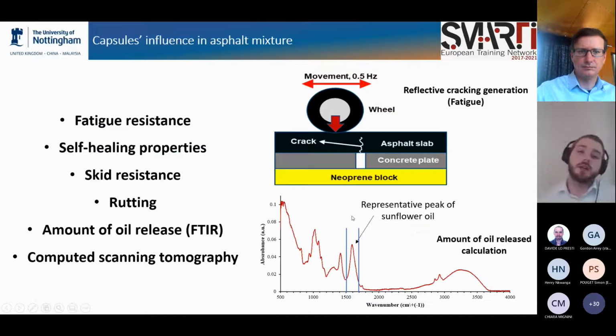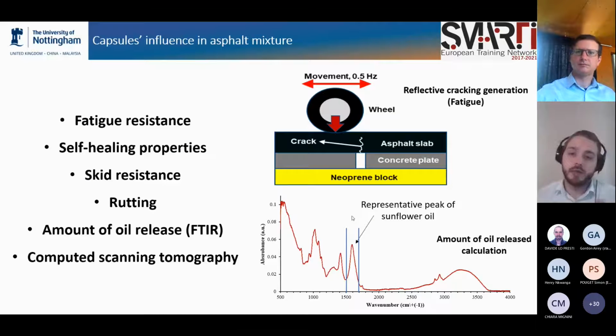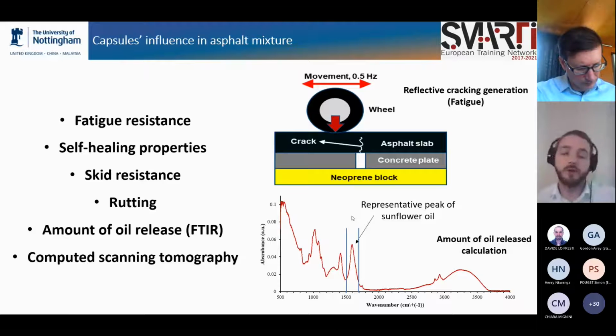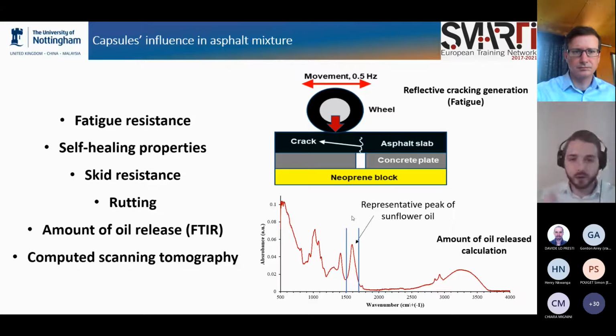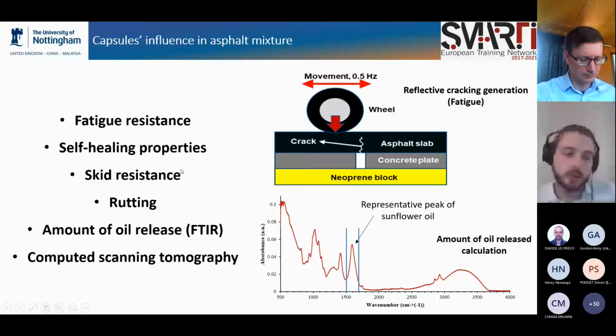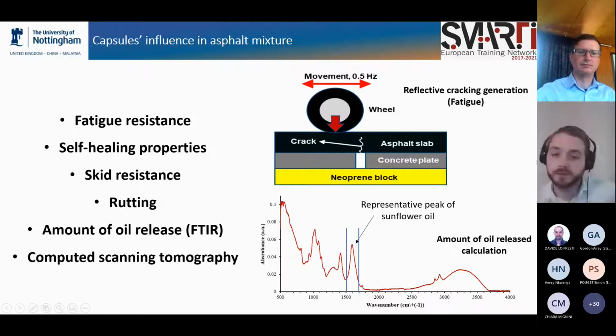So to analyze the influence of the capsules and how much we maximize the self-healing properties, we decided to use a wheel tracker in order to simulate the traffic loads, and we analyzed the fatigue resistance and the self-healing properties just by seeing how many cycles of the wheel track were added after the addition of the capsules. We also analyzed the skid resistance and the rutting, and the amount of oil released by FTIR spectroscopy after the application of the loads, and also the computed tomography scanning, as I said before.